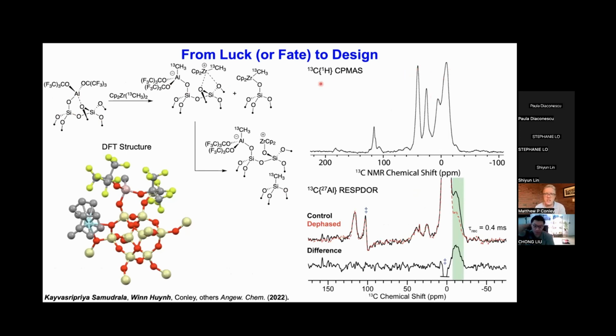We have 4 C13 labeled peaks. This is for the zirconium alkyl cation. This peak here is for the reaction of residual silanols with the bis-CP zirconium dimethyl. This site here is from the alkyl silanes that form from alkyl transfer on nearby siloxane bridges. And then this is the aluminum methyl site, which we can unambiguously confirm using this RESPDOR experiment, which reintroduces aluminum dipolar coupling under MAS and results in signal loss, which we can then unambiguously establish that this is the aluminum methyl, but we can also then extract a distance of this aluminum methyl as well. And that's done in collaboration with Aaron Rossini's lab at Ames.